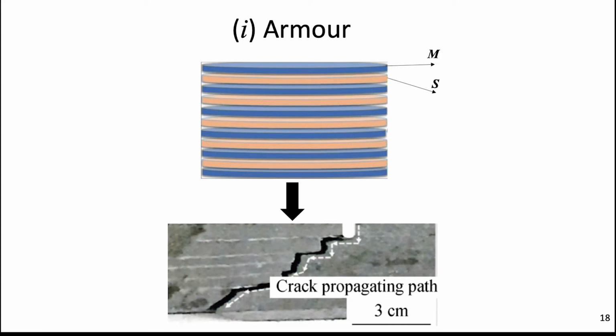This is very similar to the principles that nature uses in seashells. Probably when you have been to the beach, you have seen that oysters and other forms of shells are incredibly tough. If I try to press them, it's very hard to produce a crack, and that's because they produce these layers that grow on top of each other. That's exactly how nature works. The layered seashells are so tough because, like 3D printing, they produce layers of different properties that make crack propagation so difficult.